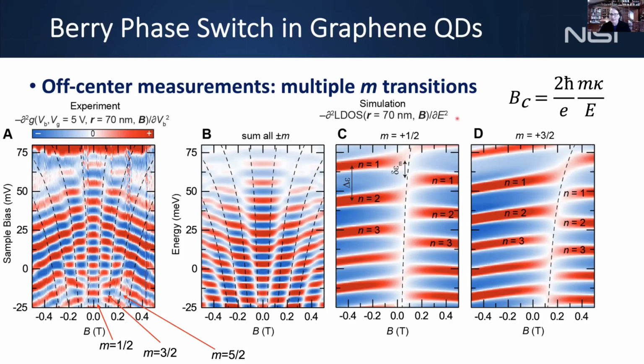And if we just plot this expression for the critical field here by the dashed lines, you can see it agrees extremely well with all those critical field values. And we can see switching behavior all the way up to m equal 9/2. So this shows you very nicely the Berry phase physics in these graphene quantum dots that you can access completely with the local probe measurements.